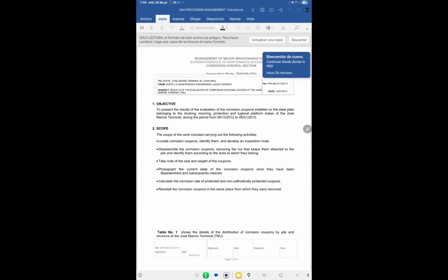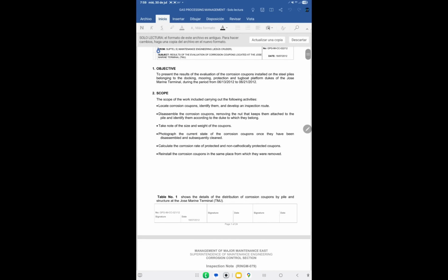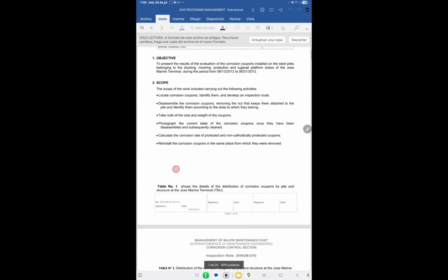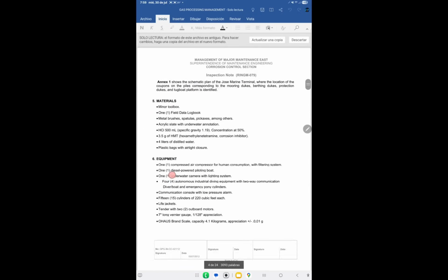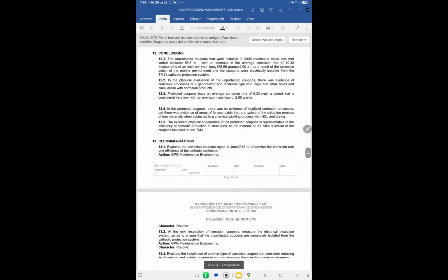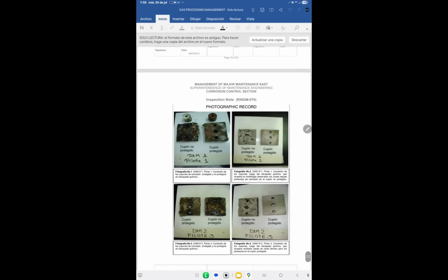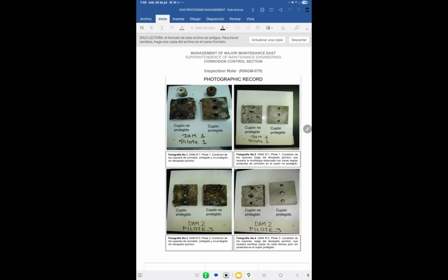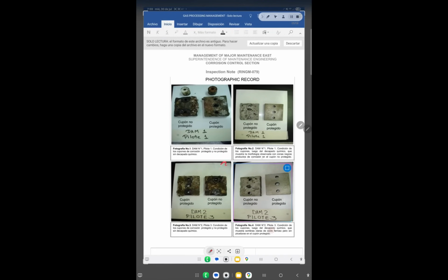Normally, for the regulatory authorities, I demonstrated the effectiveness of the cathodic protection through corrosion coupons. This is a technical report, but I want you to look at the photographic records of the coupons with protection and the coupons without protection. Take a look at this. These are coupons that I installed as I showed you in the schematic. I already had identified where I had installed them, and this is how the coupons looked when I removed them, both the protected and the unprotected ones.